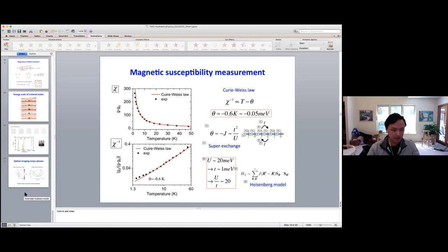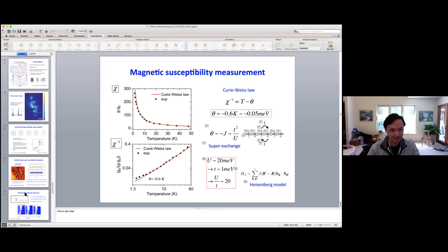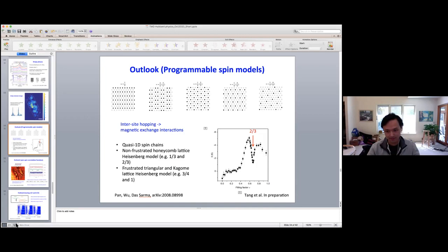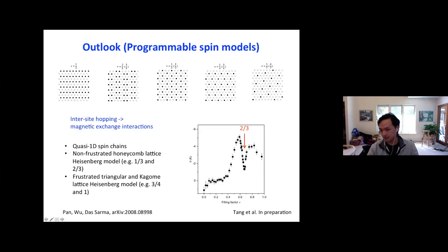Do I have data to show? Yeah, we have studied it. I don't have the data, well, but this is the extracted Curie-Weiss temperature, basically from the same measurement where we measure the temperature dependence of chi at different filling factors. This is filling factor one. And there is some change at some charge order states, at some conventional filling factors. But overall, there's sort of a peak near about 1/2 filling.